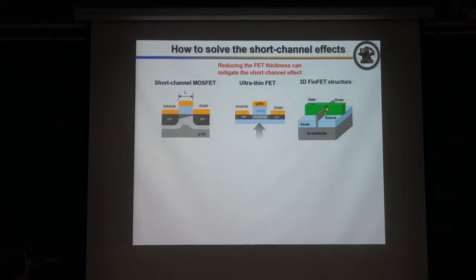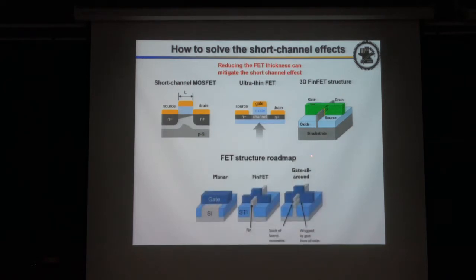And this structure also takes advantage of very thin materials. So they fabricate a fin, and this is a source and a drain, and a gate crosses at the middle. In this kind of structure you can reduce the short channel effect. So if you want to reduce the gate length, you have to reduce the thickness also. So this is now the FET structure roadmap. Conventionally, we use so-called planar structures with source, drain and gate. And then we move to so-called FinFET technology with very thin material at the middle, and this is the gate material.